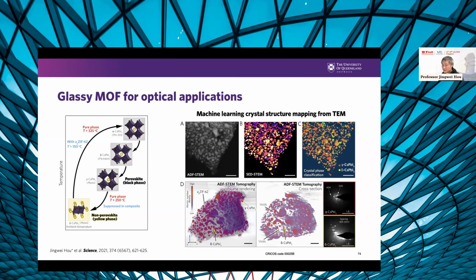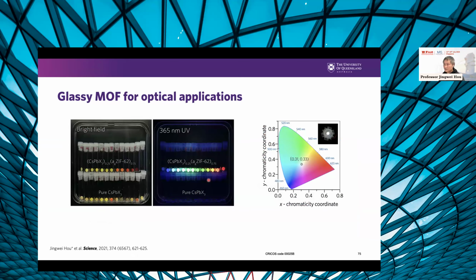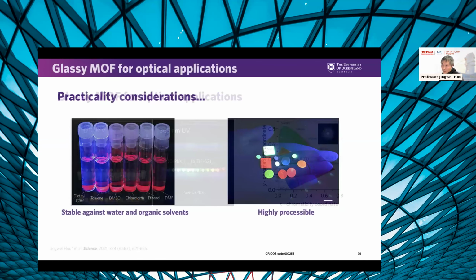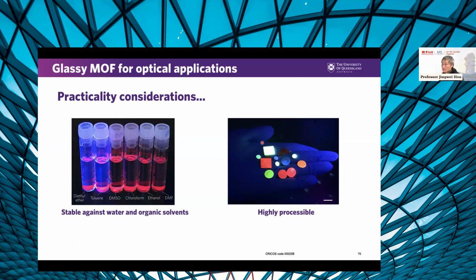We have done substantial calculations to understand the properties at the interface, properties at the phase transition, etc., and we ended up with something very efficient. Pure perovskite is pretty good, but our composite only contains 25% perovskite by weight. We can see the brightness is somewhere between 2 to 3 orders of magnitude higher. So this is not 20 to 30%, but 100 to 1,000 times more efficient compared with pure perovskite. This is very, very exciting. We can mix and blend different materials to make white light LEDs. And again, it's quite robust. We can also process them into different shapes. Super exciting.